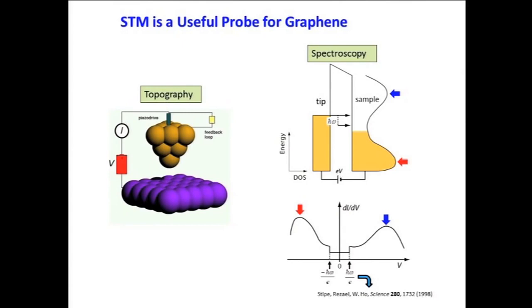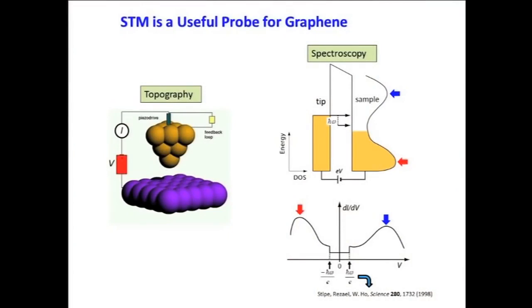Also, the STM allows us to measure inelastic excitations of small structures. And the way we do that is if we put a bias on the STM tip that's big enough so that electrons tunneling from the tip to the surface have enough energy to create an inelastic excitation, then that gives those electrons an additional channel to go from the tip to the surface, an inelastic channel, say by making a phonon, for example, and that then gives us a jump. See this little step right here? That gives us a jump in the dI/dV at the threshold energy for creating those excitations.